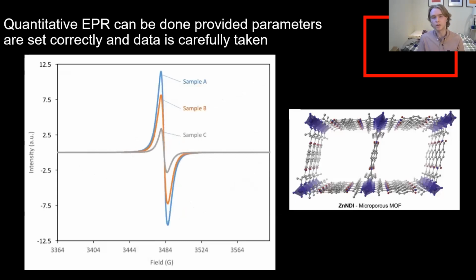So as I've already talked about, EPR can be used very well to do quantitative analysis, provided parameters are set correctly and the data is very carefully taken. This type of technique that I was planning on using here was actually something I had used previously a couple of summers ago in some research that I was doing with a different metal organic framework. In this case, the guest that was being taken into the framework was not itself a radical, but rather it radicalized the framework around it. And then based on different amounts of guest doping, we were able to get different sample curves. You see sample A, sample B, sample C, based on different amounts of doping. And from here, quantitative data was able to be collected.